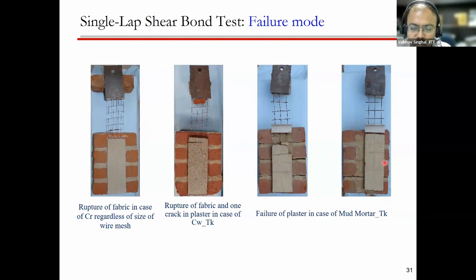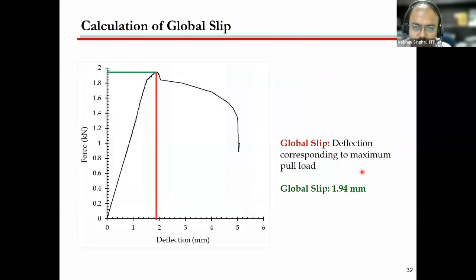So when we use the low strength mortar for the strengthening purpose, in both the cases we have used the mud mortar, and mud mortar did not perform very well because of its earlier failure and also because of debonding from the surface. Now, using this test, you can find out how much slip is expected at the design forces, at the design level of force. So this is quite an important test, which can give you an idea about the relationship between the bond stress and the slip.